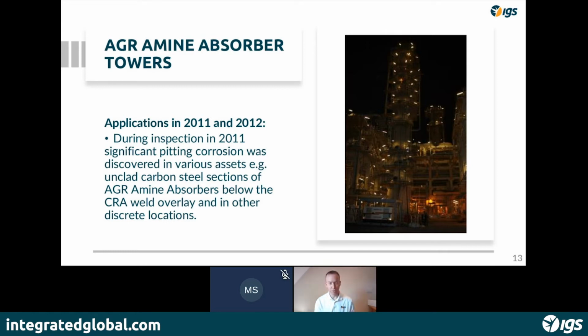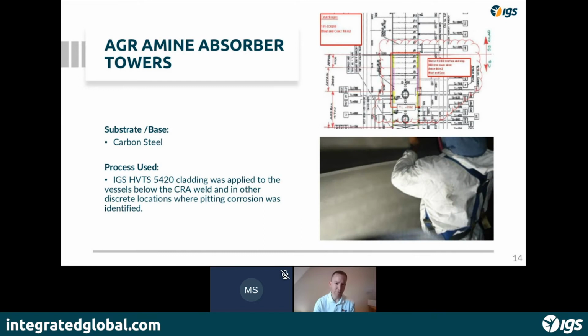Like many of these columns, the original design had a clad section in the top of the column where it had 316 stainless steel incorporated. The problems they had was below the cladding. They were having corrosion creep coming down the column, and they were seeing some relatively aggressive pitting taking place. So with IGS, we discussed with the client how to install a corrosion-resistant barrier using the high-velocity thermal spray process. And we did this using our standard operating procedures.